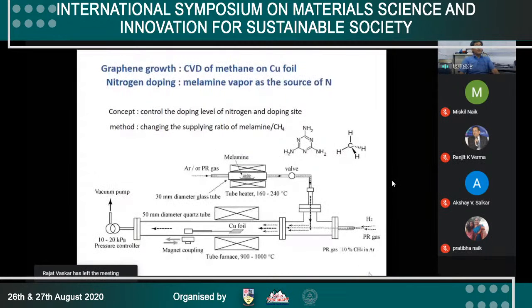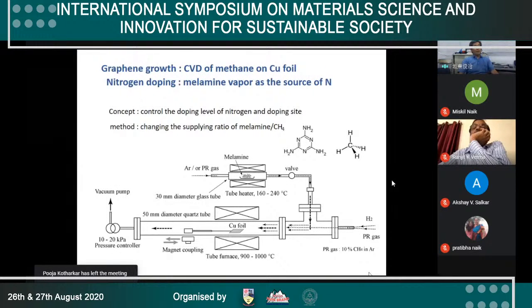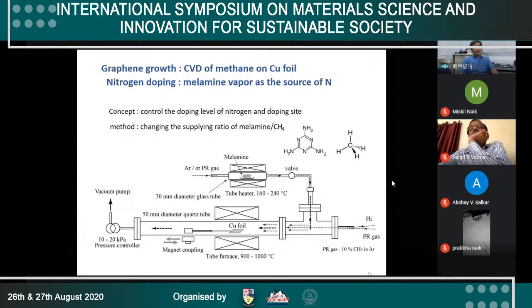When we increase the temperature of the melamine furnace to about 200 C, melamine vapor is generated and gradually carried by the carrier flow of argon or PR gas. PR gas means argon including 10% methane. It gets into the synthesis furnace set at about 950 centigrade, and we use copper foil. Okay, the next slide, please.